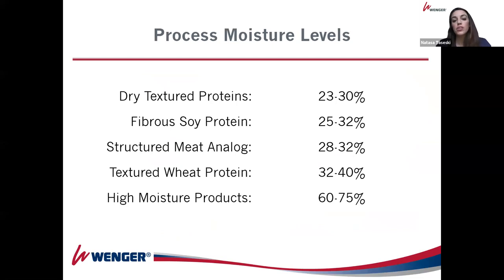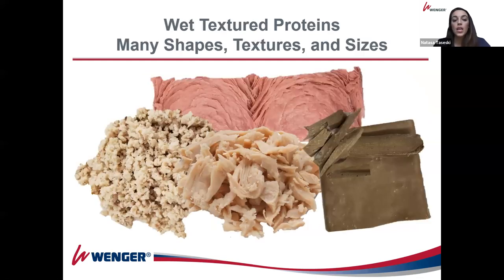So just a comparison of process moisture levels. The dry texture proteins really range between 23 to 40% moisture, depending on the kind of product category that you're looking at. Whereas the high moisture products are typically already high in moisture and range between 60 to 75%. And in some instances, you may go lower in the moisture content in these, but in your finished application that goes to the final consumer, typically this would be the moisture content. So here's an example of some different wet texture proteins and textures and colors that are possible within the process. This is also very possible with the dry texture proteins as well, where you're able to create a range of colors and shapes.